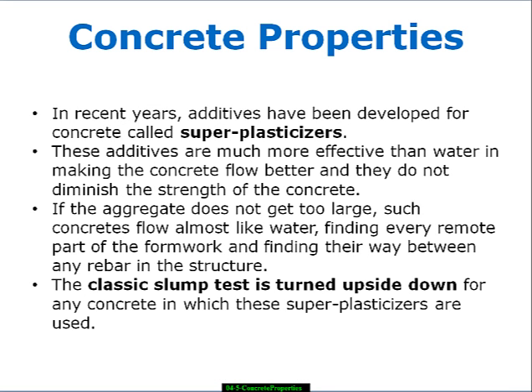In recent years, additives have been developed for concrete called super plasticizers. These additives are much more effective than water in making concrete flow better, and they do not diminish the strength of the concrete. If the aggregate does not get too large, such concretes flow almost like water, finding every remote part of the formwork and finding their way between any rebar in the structure.